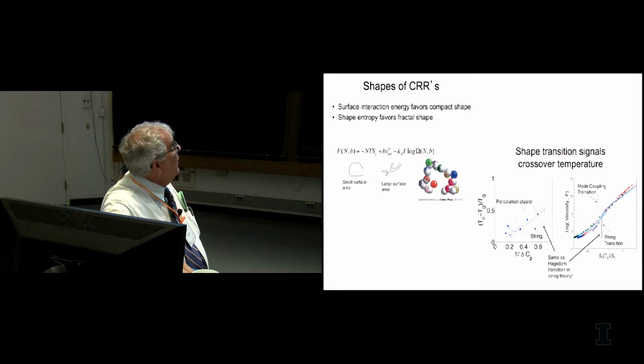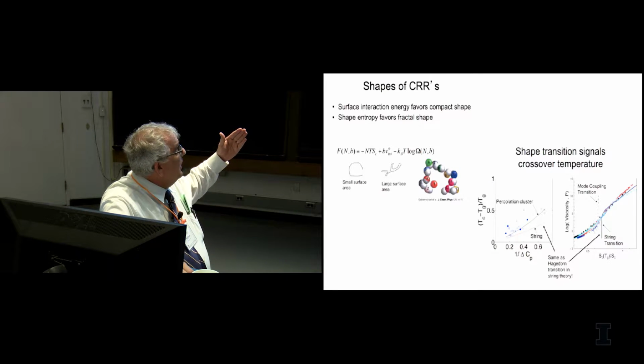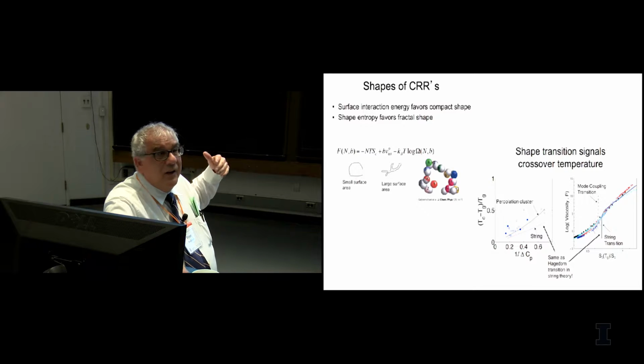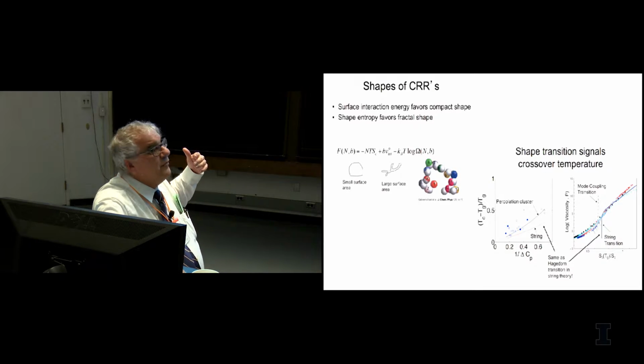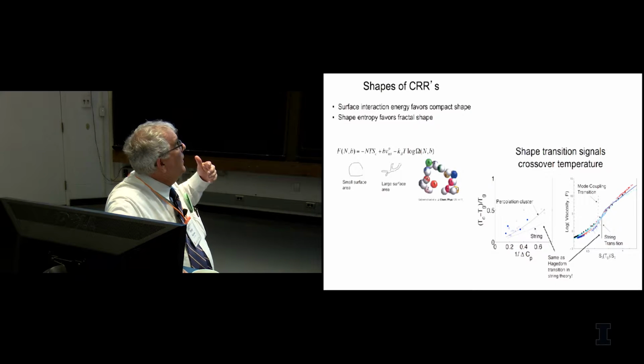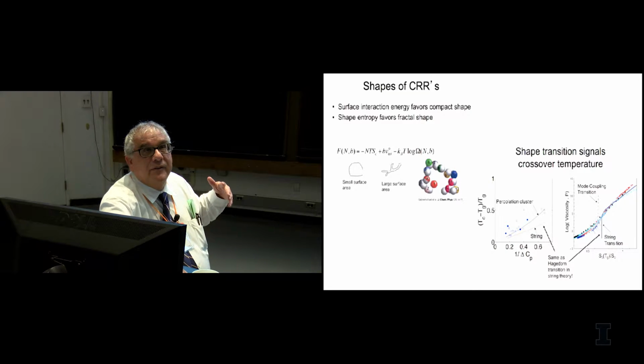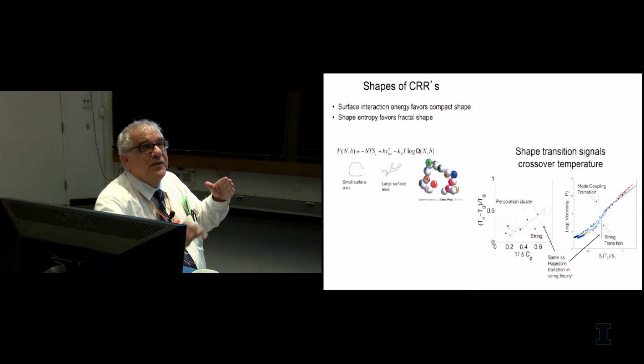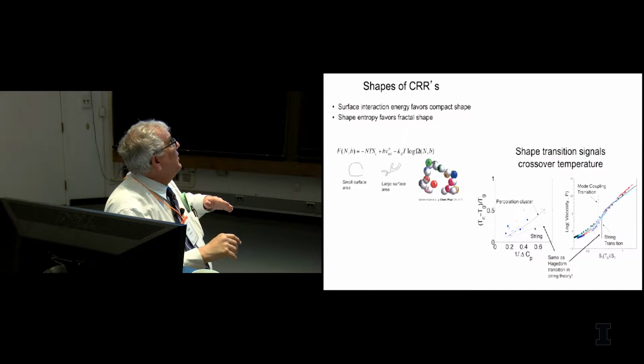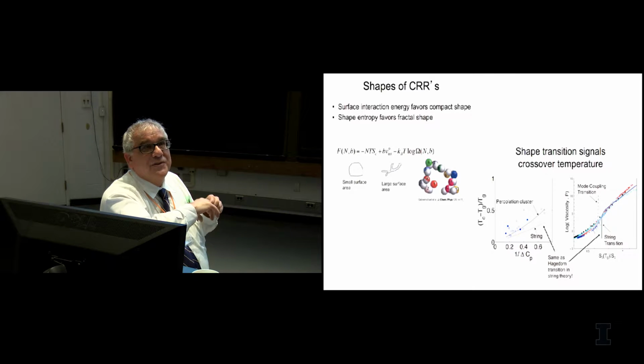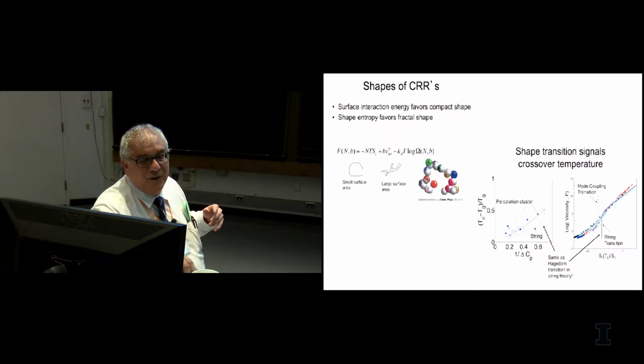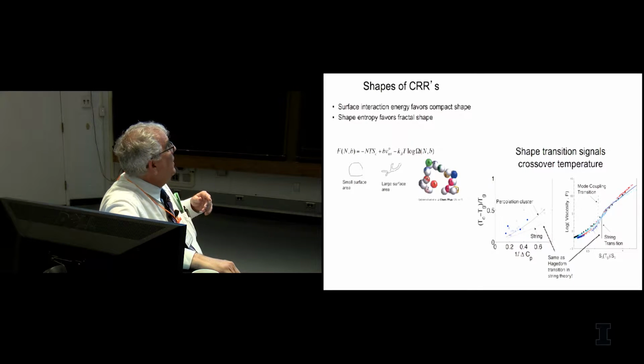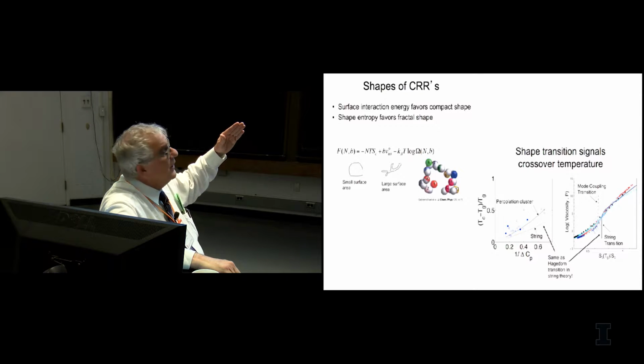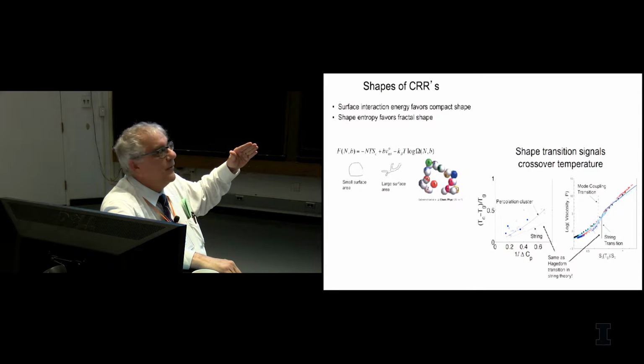a contribution that comes from counting the number of ways you can move. Well, one idea would be that those things are what are called lattice animals, and they're roughly percolation clusters. They have an entropy that grows linearly with n. And so you have an energy cost of mismatching things that's linear in n, and you have the entropy gain that you get because there are many different states, and you get an entropy gain by trying to figure out what the shape is that you would want to make. So above a certain point, this is a completely downhill process, and that's why you can't be trapped.